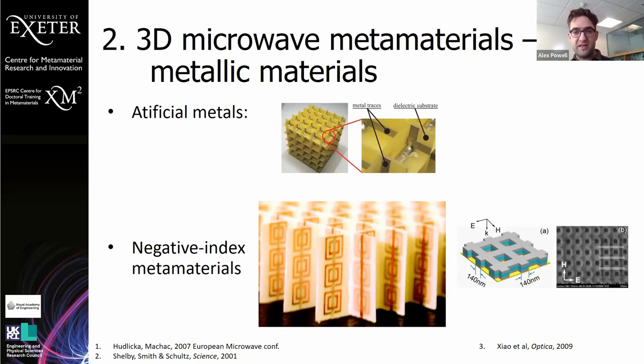Some of the foundational papers to show this, 10, 20 years ago, were printing all these things on 2D circuit boards and putting them together. In this bottom one, I should get my pointer up actually, they combine wires and split rings to give you negative permeability and permittivity and create these negative index materials. That's a classic metamaterials experiment. And this paper is by Hudlicka, and they created this negative permittivity dilute metal, again by gluing circuit boards together. Some people have done stack structures for the optical as well, but really it's layers of 2D that everyone has used to make these materials.